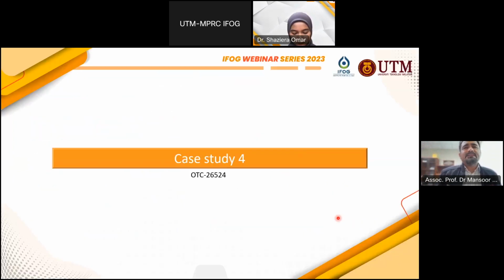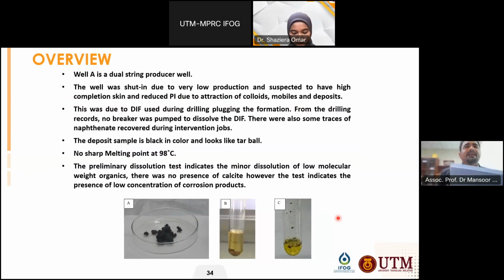Okay, so case study 4. This one is well A, a dual string producer well. The well was shut in with low production, and a completion skin was suspected, along with reduced PI due to the attraction of colloidal, mobile, and deposit. This was due to the drilling fluid used, which caused plugging, and there was no breaker pumped to dissolve this drilling fluid. There were also some traces of naphthenates recovered during the intervention job. The deposit sample, as you can see, was black in color and looked like a tar ball, with no sharp melting point at 98 degrees centigrade.